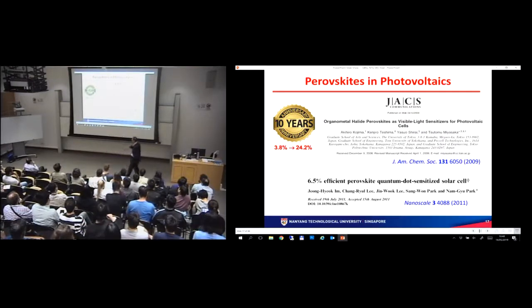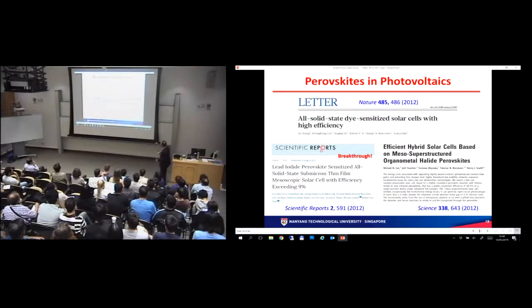So, and this is a very amazing feat for a solution process system. Now, Professor Nam-Gyu Park picked it up and worked on this, but he was still based on the liquid electrolyte. He still managed to improve the efficiency to about 6.5%, but it was still plagued by a lot of stability issues. Now, Kanatzidis then used this cesium lead iodide system as a hole conductor, still under the premise of a dye-sensitized solar cell, making an all-solid-state solar cell.